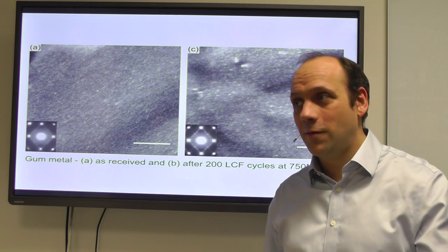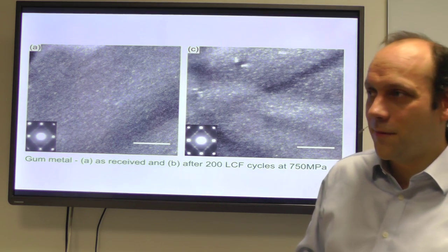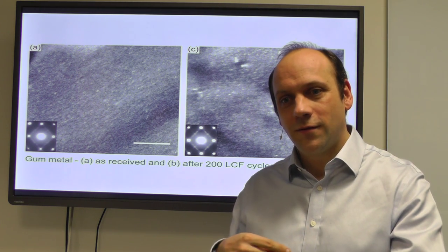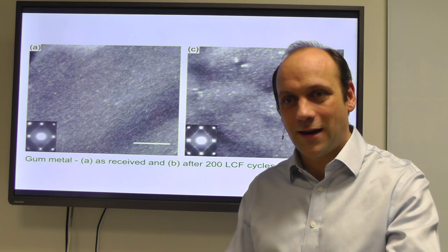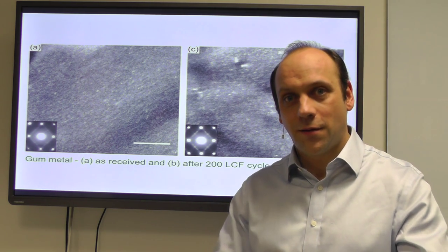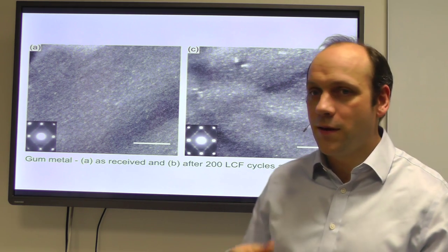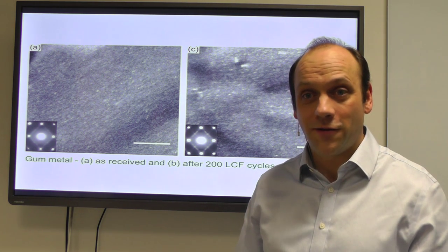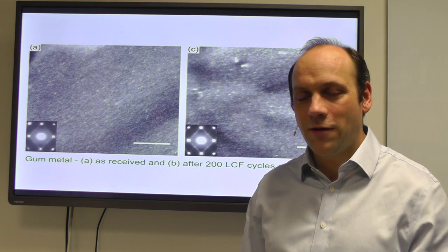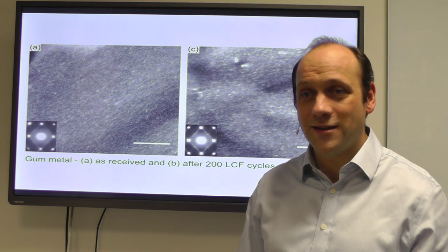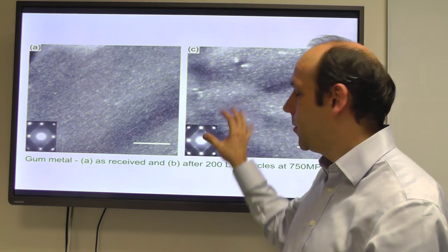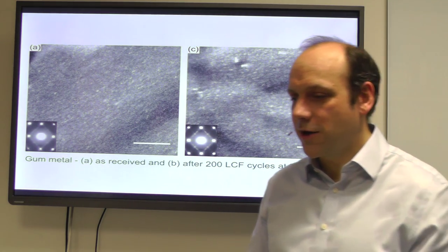I can think of two possibilities. There might be more. One is that in moving the dislocations around, you're making diffusion quicker. You can have pipe diffusion down the dislocation, so you're allowing it to form isothermal omega. The other is that you've got a pressure field, or a stress field, around the dislocations, and if you have lowered the formation pressure of the omega phase enough, then that might be enough to nucleate omega around the dislocations. I think I prefer the latter explanation because I think we see it in TEM, but it's very difficult to distinguish.